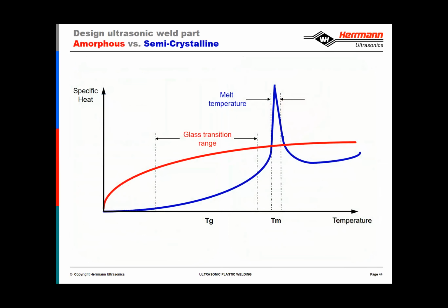So here, if we overlay the melt characteristics of the two materials, you can see the red line, amorphous resins, that when they reach that glass transition point, they continue to gradually soften and then eventually become liquid. Whereas the blue line, the semi-crystalline line, the material doesn't soften, but rather it very sharply and very quickly melts when it reaches that melt temperature.